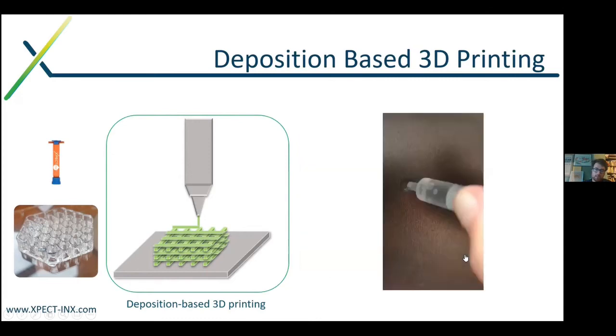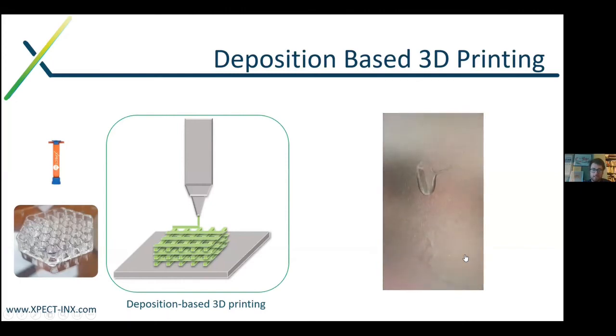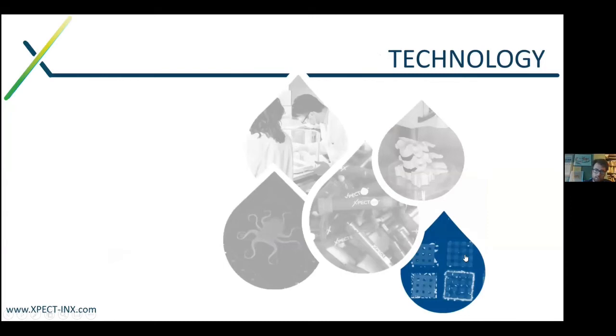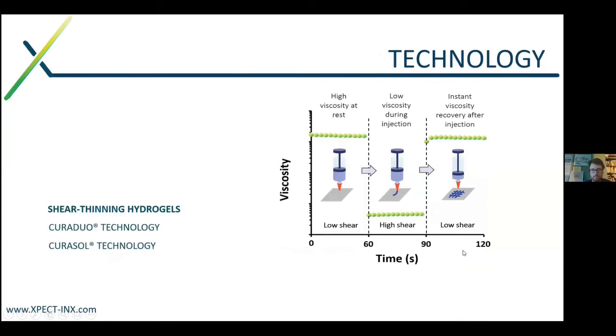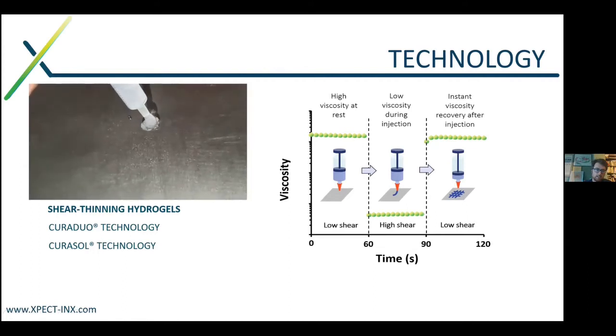Unfortunately, most materials, most liquids behave like this. Once they extrude, they just keep on being liquid, and it's very difficult or impossible to print. Now, fortunately, there's some technology which can convert one into the other, which is called shear thinning materials. So shear thinning materials or shear thinning hydrogels are materials which have a high viscosity at rest, so they are very strong or resilient when they're untouched. When you exert a force on that, the viscosity decreases rapidly and you get a very liquid material. So this is what happens in the nozzle. And then once you remove the external pressure, so once they are deposited, the viscosity increases very fast and they maintain their shape. And this basically looks like this. So you can see it extrudes really easily, but it maintains its shape after deposition.